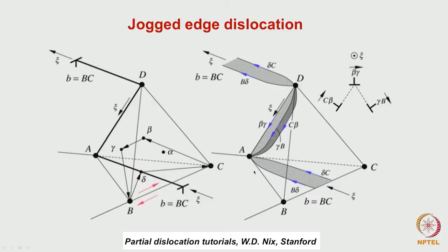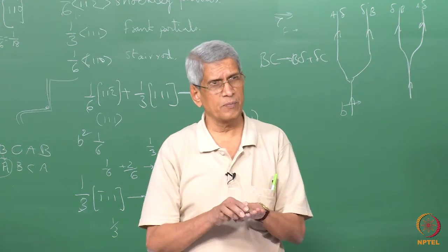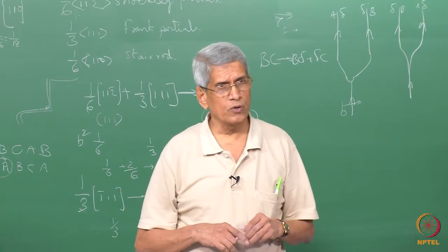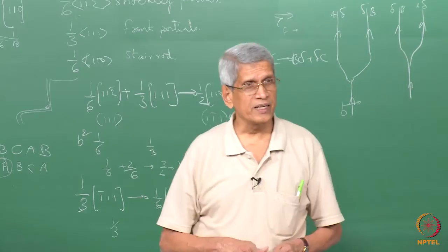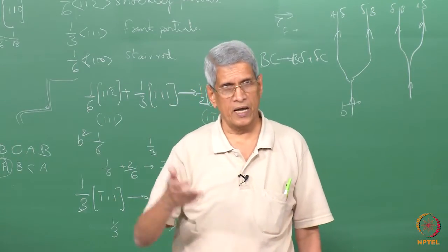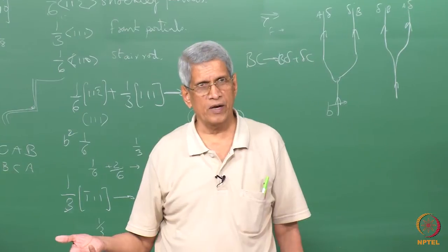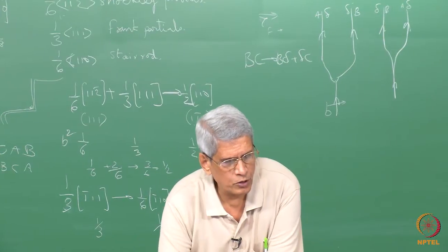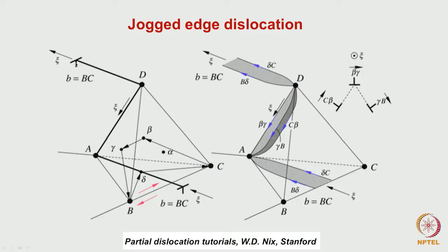Another case which we can consider is, what we considered so far was essentially dislocations in two planes, perfect dislocations which are split into partials. When the stacking fault energy is low, the dislocation itself will be curved, right? One part will be lying on one plane, another might have cross-slipped, and then moved into a parallel slip plane. Such cases, where the dislocation splits into partials, are what is being considered. Consider this case: the Burgers vector is the same, BC, for these two segments. This dislocation essentially will have a Burgers vector BC, okay.